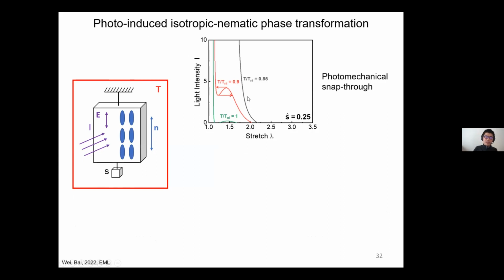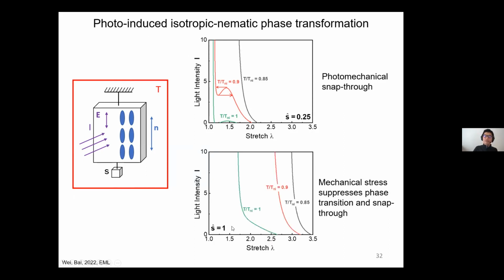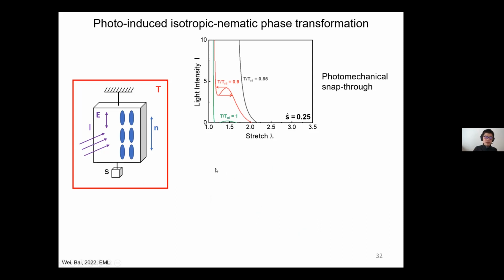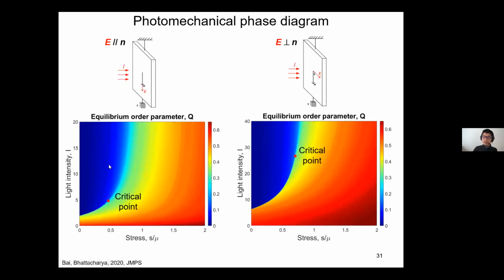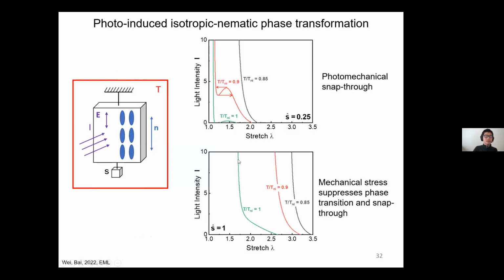With a different temperature, it might be a different story. Even with a different stress, it can be a different story. The stress can actually also suppress this first order phase transition and the snap-through. You can see it from here, right? If the stress is too high, you don't have a first order phase transition. I have to say, in reality, this might not happen, because in liquid crystal polymer systems this first order phase transition usually becomes second-order-like, but you can still expect a very sharp change of deformation close to this region, okay?